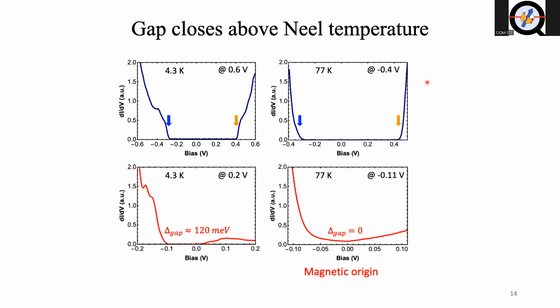Anyway, so what we did further, to make sure that this gap is magnetic related, is we raised up our temperature to be 77 K. In this case, it is above the Néel temperature, and we still see a similar sizable low bias conductance region. But when we zoom in, we can see this gap disappears. The disappearance of the gap above the Néel temperature is another evidence that the gap is of magnetic origin.